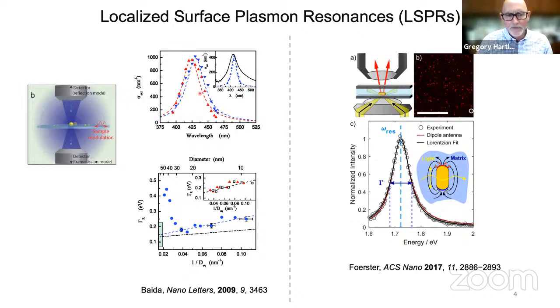So what you see here are some measurements on single particles. We're looking at a plasmon resonance for particles that's commonly called the localized surface plasmon resonance. You can measure the frequency or the wavelength of the resonance and its width. There are a couple of different ways of doing that. The most common ways are these spatial modulation experiments over here on my left, or your left, where you modulate the sample in and out of a focused laser beam, and you use that to record a signal and change the wavelength to get a spectrum. You can also do these experiments through light scattering. That's actually typically a little bit easier, where you just look at the scattered light from a single particle, and again, you can find a resonance, you get the resonance frequency and the line width, and the line width would tell you about the time scale for the dephasing of the plasmon. These line widths are on the order of 100 millielectronvolts, which would be a dephasing time of about 15 femtoseconds, so very fast.